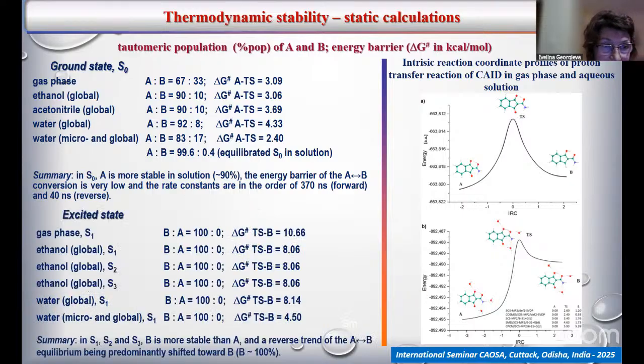What happens in excited state? The stability of both tautomers changes, and B becomes the more stable tautomer, and the population of B tautomer is about 100%. The same in gas phase; in solvent also, the most stable tautomer is B, and the energy barrier is higher. So in excited state, the trend is reversed, and the equilibrium is predominantly shifted towards the B tautomer.